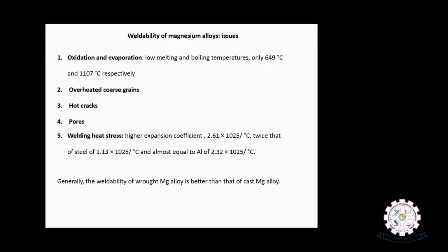So oxidation is a big problem with magnesium, and also the melting point and boiling point of magnesium are lower. Therefore, in fusion welding processes, sometimes we get temperatures of more than 1000, 2000, 3000 degrees centigrade in the flame. At such temperatures, magnesium may get evaporated. That is another technical problem. And overheated coarse grains result in the magnesium weld joints, and hot cracks during the cooling process.